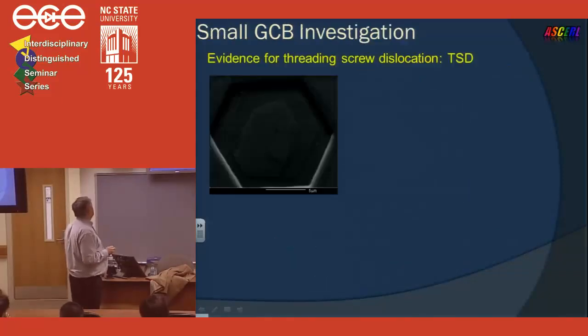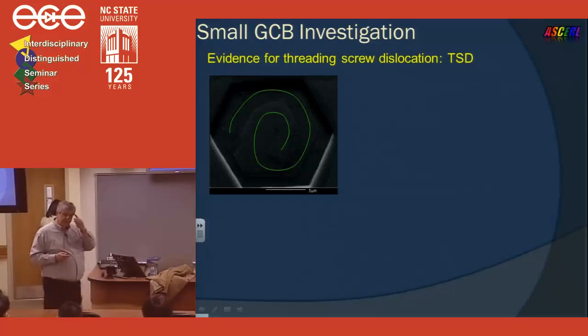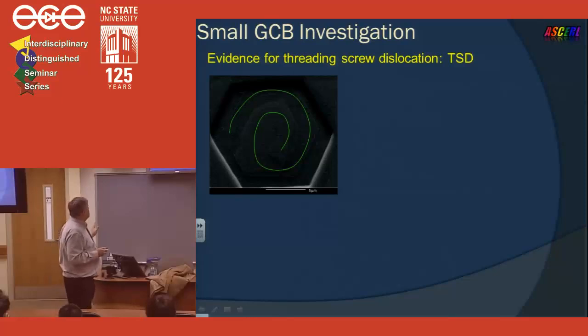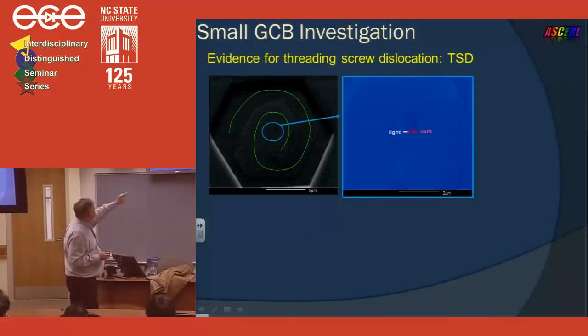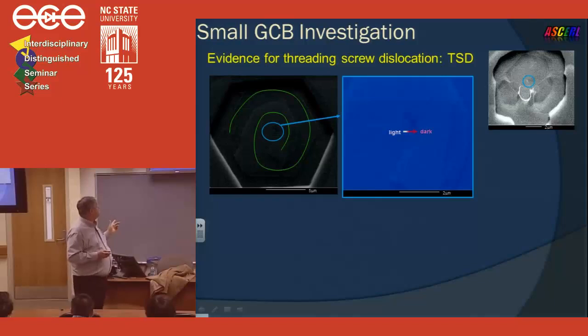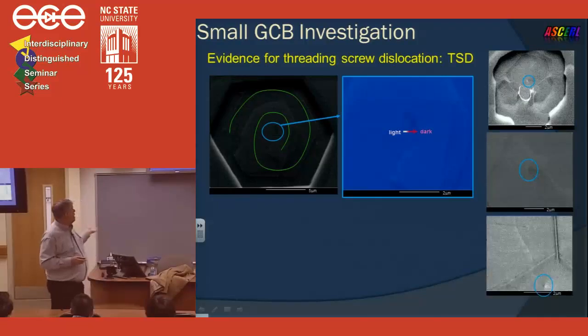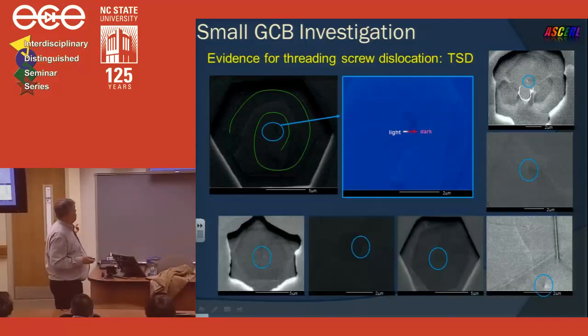There we go. So when we looked at one of these graphene-covered basins, and you can see it more clearly in the monitors, you can see the spiral pattern. And so right away you're thinking, okay, it's probably a threading screw dislocation playing a role here. So to determine precisely, we need to look at the contrast of the screw dislocation. And you can see here it goes from light to dark, going from left to right. And we've looked at a lot of these graphene-covered basins, and they all have the same feature. So let's zoom in on this feature.